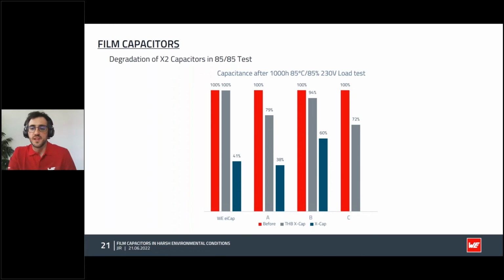Here we represent the same result from the 85 load test, and we compare our parts with 3 competitors. As you can see, the results are very varied. Competitor A performed well with the regular and THV components, but competitor B did have more robust regular X capacitors. Competitor C, on the other hand, did not offer THV parts, but the normal parts did actually perform better than any of the regular normal capacitors.